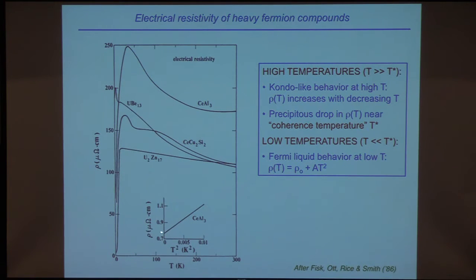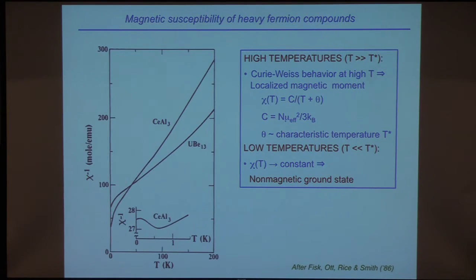And then you can see for this one, rho is proportional to T squared, so that you see the Fermi liquid type behavior. And then for magnetic susceptibility, for these two examples, at high temperatures, it resembles a Curie-Weiss law. The moment's close to the effective moment that you would predict from Hund's rules. And then you get a negative Curie-Weiss temperature, which is a measure of this interaction temperature T star.